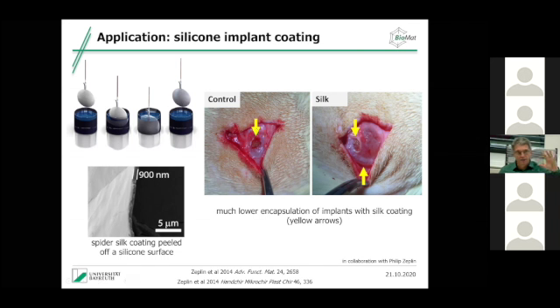What happens is the cells go to the surface and would like to destroy this foreign material, but silicone is pretty strong, so it's not biodegradable. And what the cells then do is start to encapsulate it. They start to make cartilage surrounding this implant, and make a capsule. For the rats, that's not a big issue. For human beings, that can be an issue, especially if you're a breast cancer patient, because you have a depressed immune response system. Therefore these capsules can really cause severe side effects, because what might happen is an inflammation, and in about 25% of the breast cancer patients that got a silicone breast implant after their surgery, this implant has to be removed because it causes problems, and this is of course not nice for the patients.